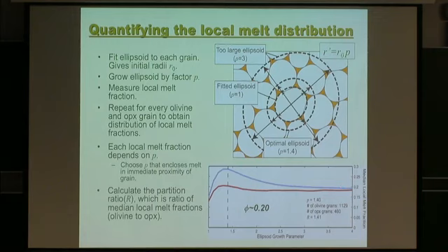They start not very different and end not very different, because this is too large a region and too small a region, but they always come up with some peak at a size of around 1.1 to 1.4 of the original grain size. He then used that difference as an indicator of the melt redistribution.